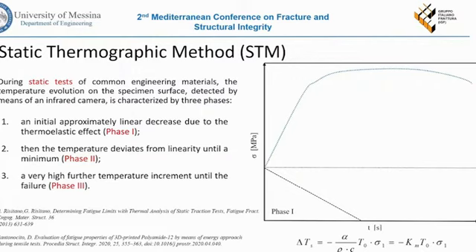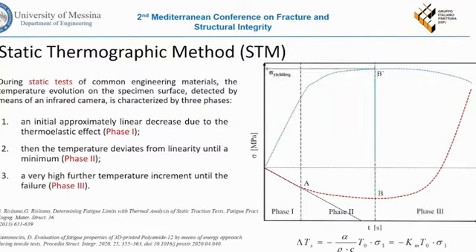The first phase shows a linear decrement of the temperature according to the thermoelastic law of Lord Kelvin. Then the temperature deviates from linearity in a second phase. And finally, in a third phase, we reach an overall macroplasticization state until the failure of the specimens. So if we are able to assess the transition between the first phase and the second phase, we can correlate this macroscopic stress with a damage stress that introduces in the material the first microplasticization.